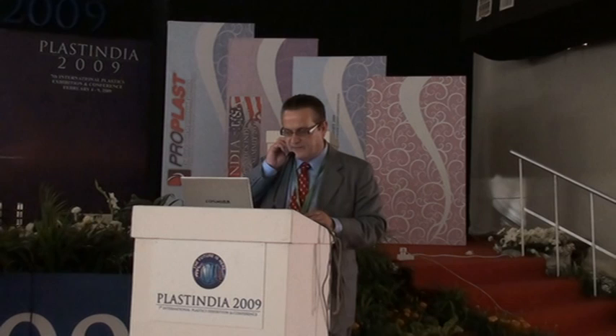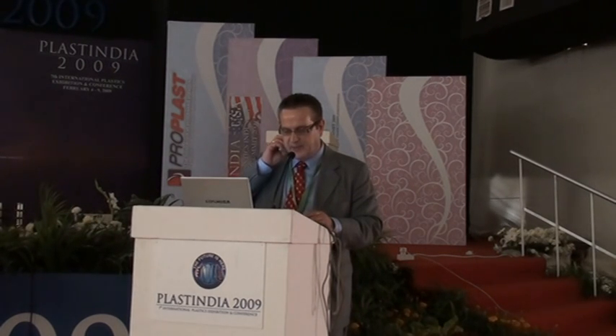This is an example of an automotive application, and you can see where we have the conformal channels following the shape of the mould tool. Again, this is showing how the construction of the mould is. We have our stainless steel cavity shell, and in this particular mould we have an aluminium conformal channel base, and then we insulate it with a resin plate. This is very important because we don't want to heat the whole mould bolster, we just want to heat the cavity plate.